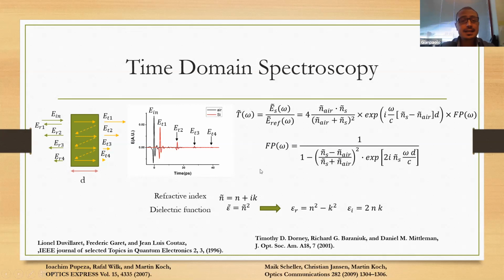What I want to say in these slides is that basically we have a way to simply obtain information on the refractive index and the dielectric function of the sample. I have to say that this relation between the refractive index and the dielectric function works only with non-magnetic materials, which are the samples we are analyzing in this case. The dielectric function is very important to our aims, because the real part of the dielectric function gives information on the phase of the material. When it's positive, we are dealing with something that is going to become an insulator. When it's negative, it is a plasmonic medium with metallic features.